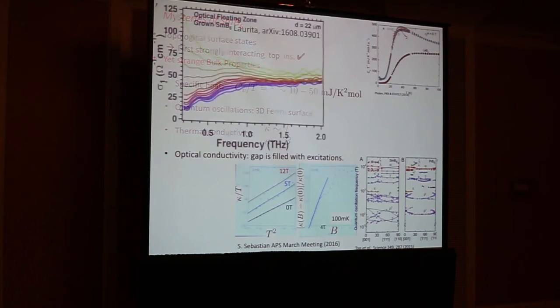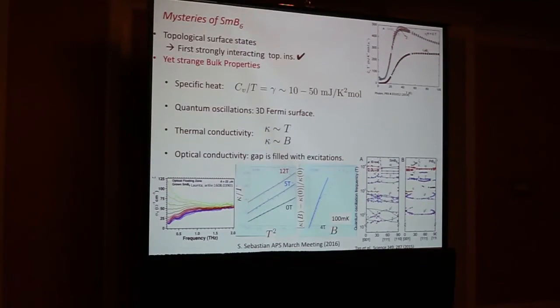Okay. And the optical conductivity, again unpublished work, shows that in the floating zone grown systems, although it's a DC insulator, it seems to be an AC conductor with a lot of subgap states here. What's causing this? Is this connected with the linear in field thermal conductivity? Is this connected with the linear in temperature specific heat? Is this connected with the crazy de Haas-van Alphen oscillations? This is the mystery of the material, and it's got theorists scratching their heads.